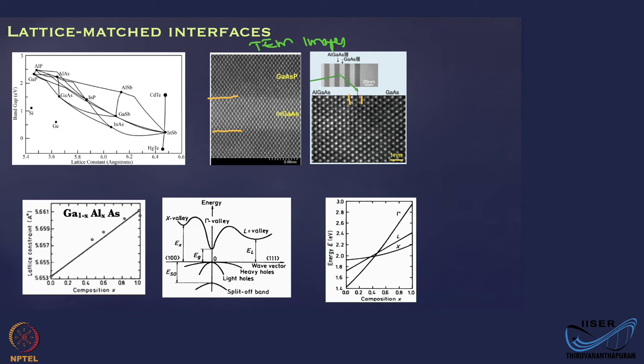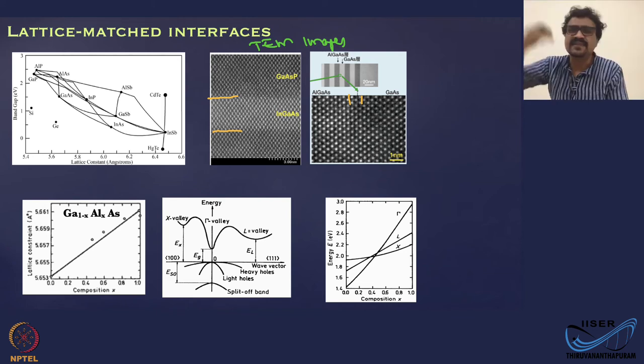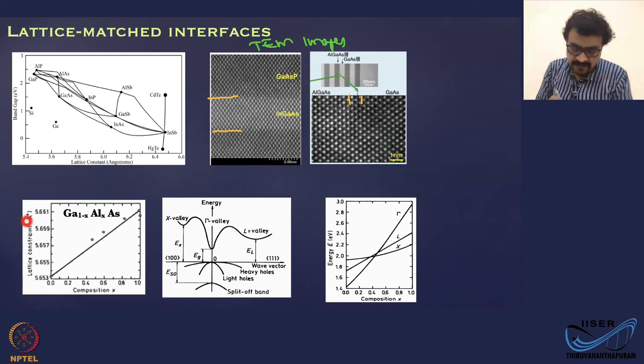That means the electron which moves through this interface is not going to feel any difference between that side and this side. Of course, it's going to see a difference in the energy of the two sides, the band gap on the two sides, but there are no defects. It's perfectly periodic. This graph here is showing you how the lattice constant varies as you change the composition, because one side is gallium arsenide, the other side is aluminum arsenide. You go from gallium arsenide to aluminum gallium arsenide by replacing the gallium with aluminum progressively. So that is actually gallium 1 minus x, aluminum x.